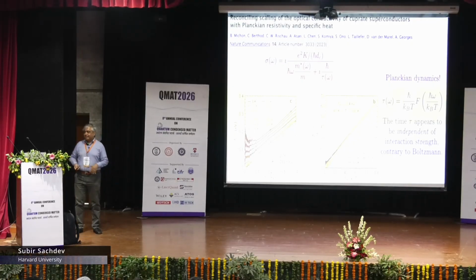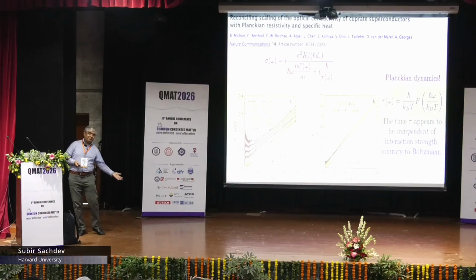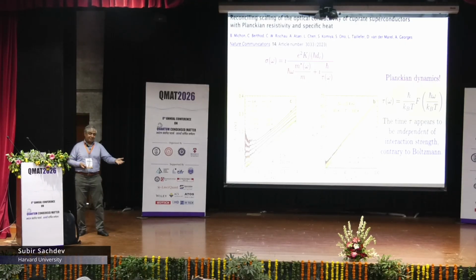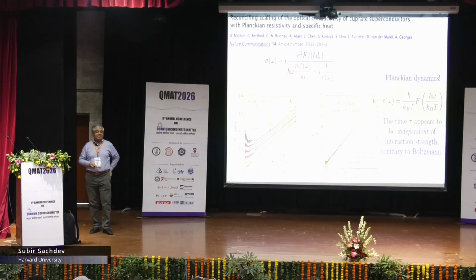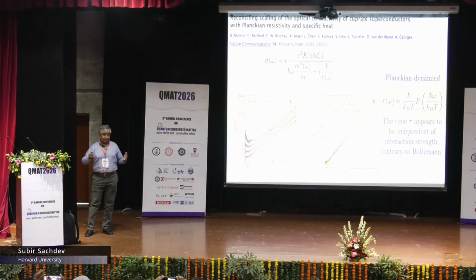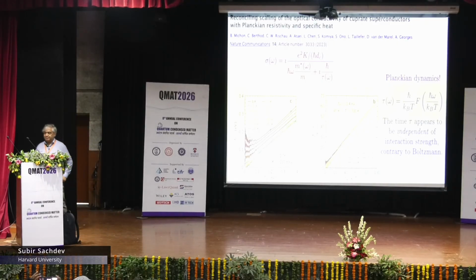So, and in fact, this kind of behavior is seen in many materials, in twisted bilayer graphene, in cuprates and pnictides, and so on, which have many, many different energy scales over several orders of magnitude. But tau is just the Planckian time. So that's a remarkable universality. There's a further universality of this as a function of omega over T.